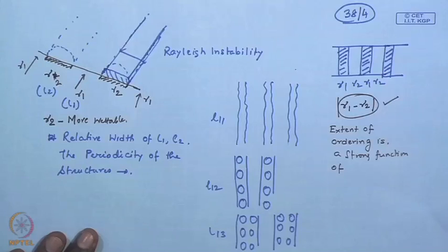In fact, they could show that there exists a critical value of delta gamma, that is the in-plane wettability gradient, below which the ordering is completely lost. So, again these are very advanced areas in which research is still active, lot of new findings coming every year. But so, from completely random structures to this type of aligned structures.